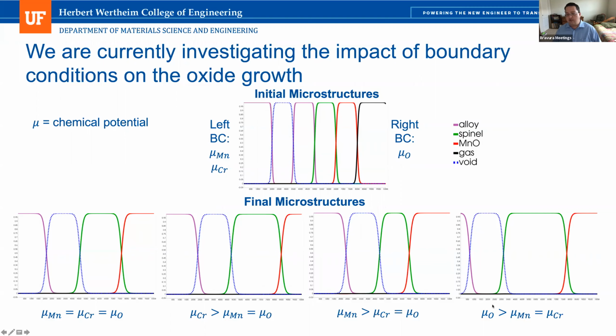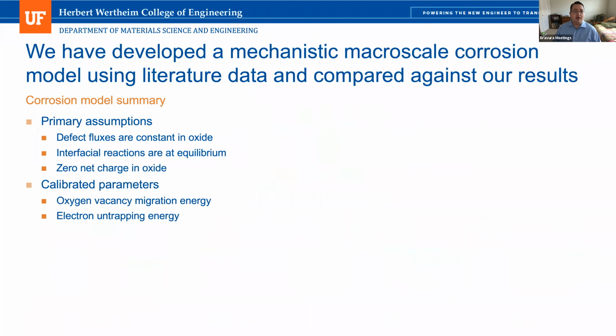However, when we have more oxygen in the system, the spinel also grows faster, and that's because the spinel is better able to accommodate oxygen than the manganese oxide. And so that could be another reason why we're seeing the faster spinel growth, in addition to just thermodynamics, if there's more oxygen available in the system. So all of this, the experiments, the density functional theory, and the phase field, are all going in to try to add our critical capabilities to the STAC tool.